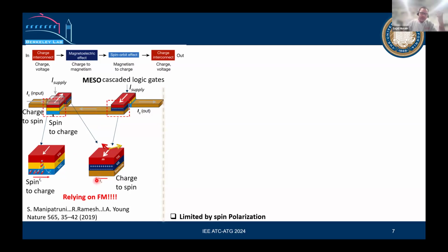Then in a second step, this magnetic material is aligned in a particular direction, and you can use a supply current to polarize the spins. Then you can convert back through the spin-orbit coupling material by the inverse spin Hall effect, back into charge. So in this process, you use a charge current as input and get charge as output, but M is working as a memory bit. The output goes into the second bit. That's electrical engineering work, so I'm not going into how to control it, but we can control the input of the second bit by the output of the first bit. That's the working principle of MESO. It's a little bit complicated, but this is the way.